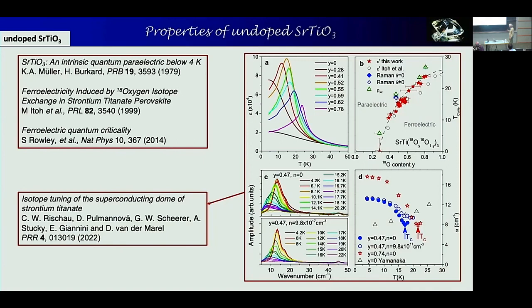So what's shown here is that effect. This is a very recent paper where we studied that in my group, where you see the dielectric constant as a function of temperature for just the oxygen 16 strontium titanate. So the dielectric constant is 2000 here, and then it starts to drop a bit. If you go to 50 Kelvin, it's maybe 300 or so. Or 500, and then if you put in oxygen 18, so at around 30% doping, this thing explodes. It goes in principle to infinity, and then if you go even higher, it is ferroelectric, and now if you warm it up, you go through a normal thermodynamical phase transition at finite temperature, where it goes from ferroelectric at this side to paraelectric at that side.